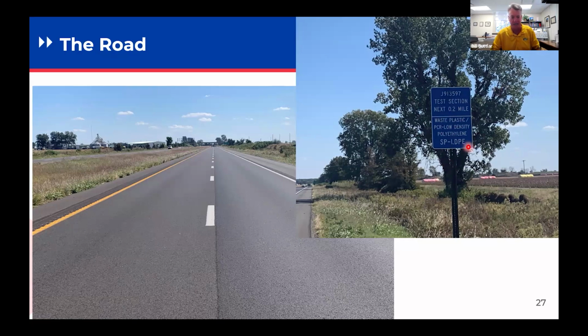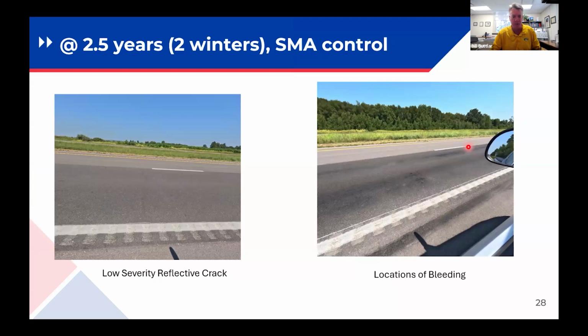There's signage for all the 9 sections so you can see what's going on where. And after 2.5 years, a couple of winters, you can see some low severity reflective cracks. This was a 2-inch overlay, but less than 50% of the reflective cracks are at low severity. And there are a lot of sites where the reflective cracks have not come through yet.